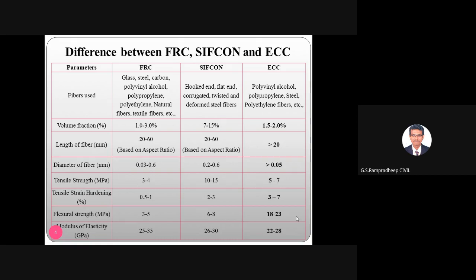based on aspect ratio, for FRC it is 20 mm, that is 2 centimeter, to 6 centimeter. I already showed you in the 13th class, mostly 5 centimeter fibers are used for FRC, that is hooked end fibers, right? For SIFCON also 20 to 60 mm. And for ECC, just note it down, greater than 20 mm. Minimum, it should be greater than 20 mm, because here we are making a thin membrane. Here we can raise the question: why are we restricting to a minimum of 2 centimeter? Why not 1 centimeter fiber?